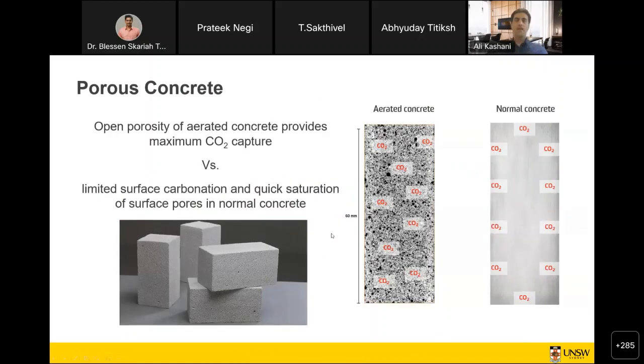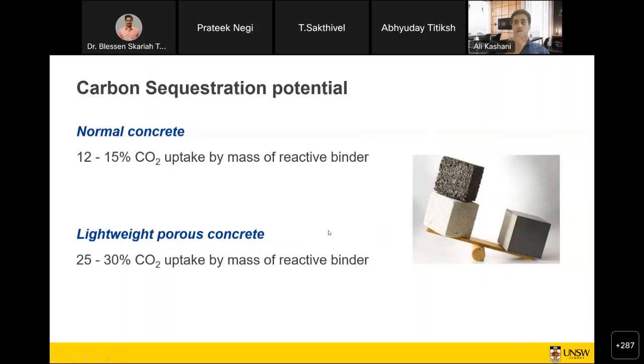But what we have done is provide a better vehicle for CO2 transportation inside the concrete. If you're familiar with measuring carbonation in concrete, it starts from the surface and stops at some stage, because the carbonation products build up and there is not much more space for CO2 to penetrate. But if the material is aerated, so we have some open porosity and permeability, then CO2 can easily get inside the samples, and so you get much higher CO2 sequestration inside the concrete sample.